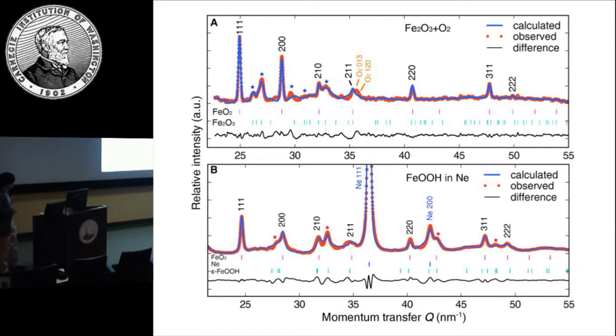Okay, so now we compare this goethite in neon versus the first experiment, the hematite plus oxygen. That one we made FeO2, and here you can see that all the patterns still agree. You also have FeO2. And later we got rid of most of the epsilon phase, so it's actually even purer FeO2.